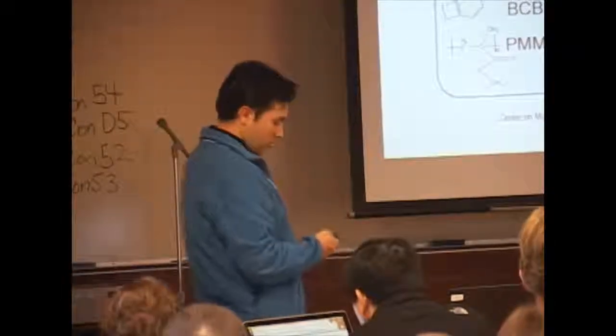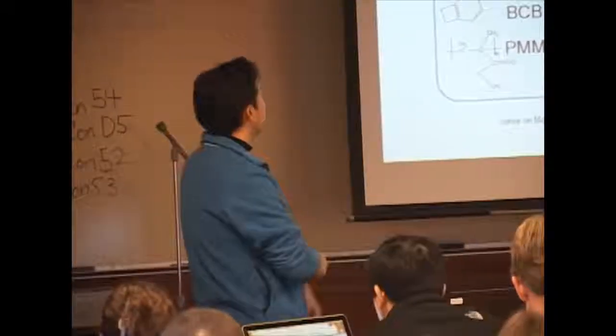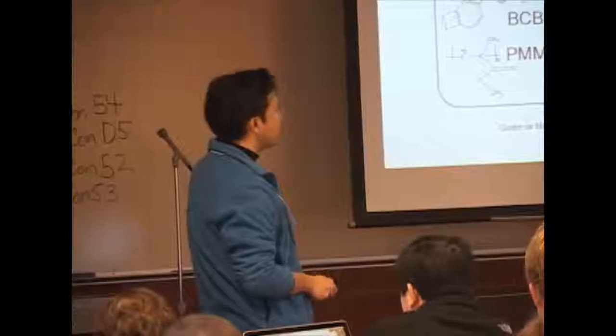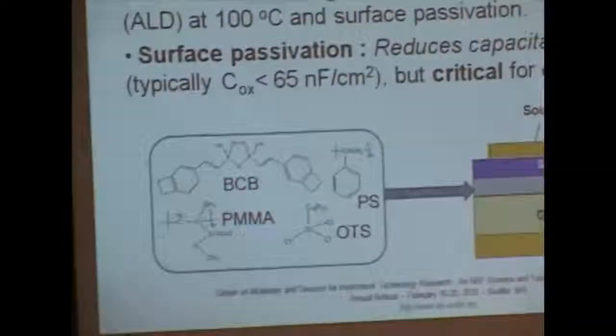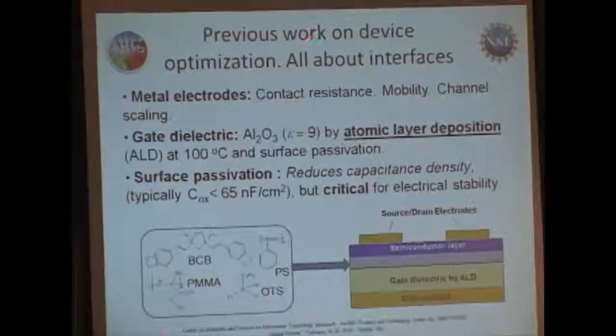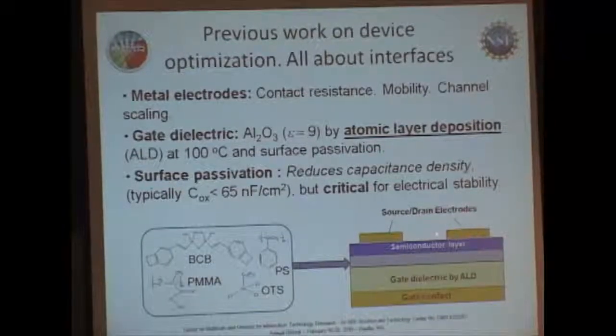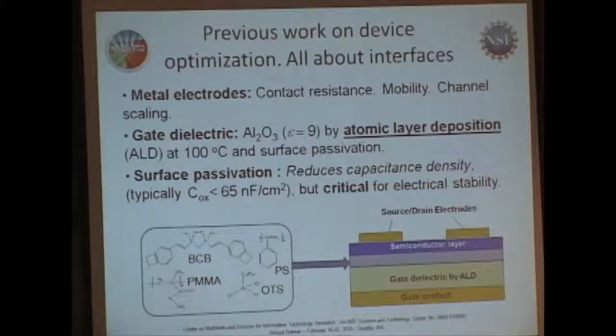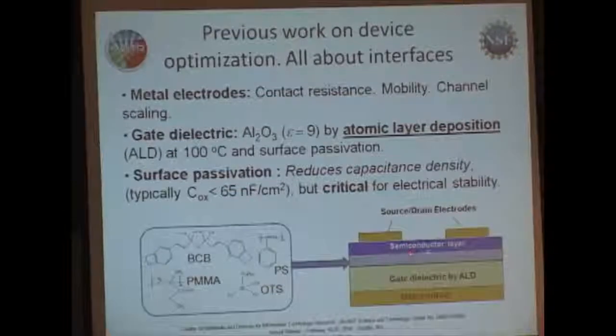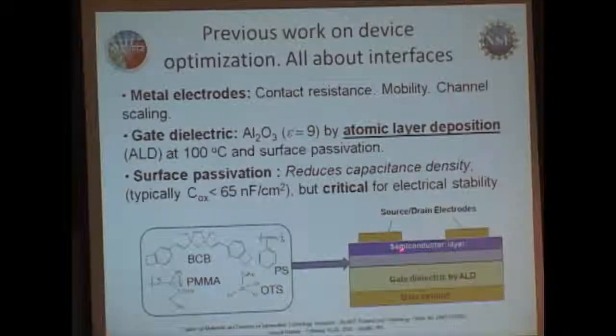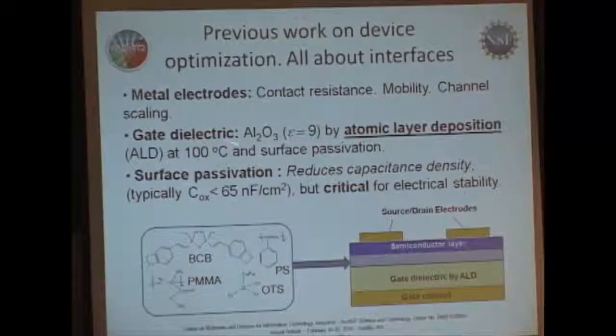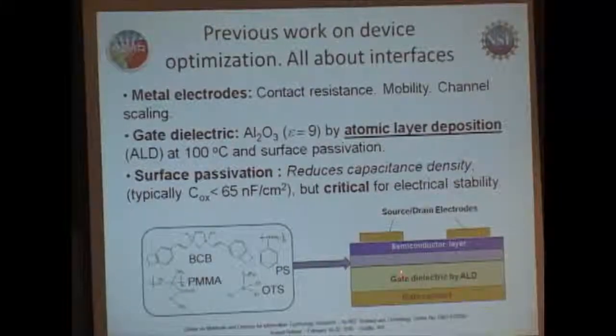To give an overview for those who haven't been around the STC long enough: in the previous year, a lot of our attention on optimizing device properties has been concentrated at the interfaces. To optimize switching performance, it's critical to select the proper metal for source and drain, and to find gate dielectrics that assure high capacitance density, preferably with no traps at the interface, so the semiconductor layer has the proper morphology for high mobility.